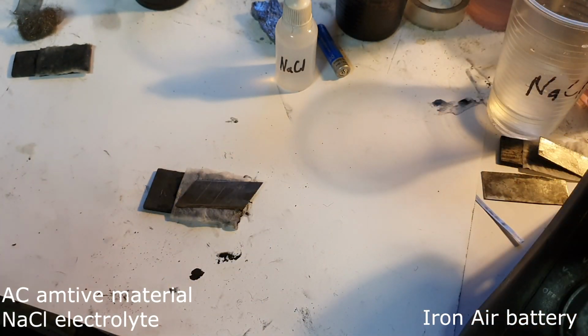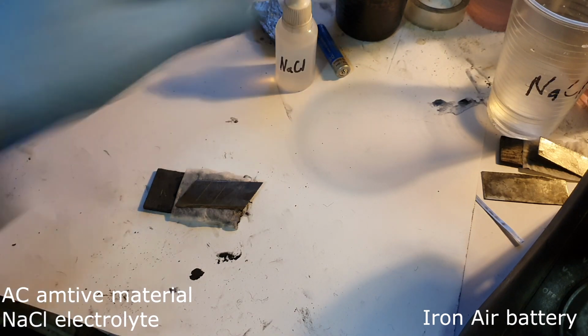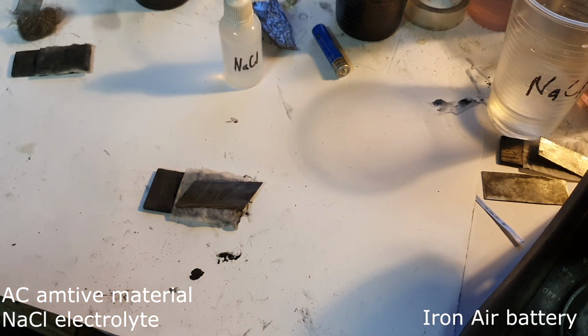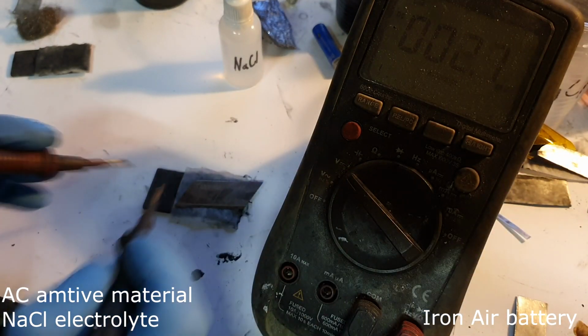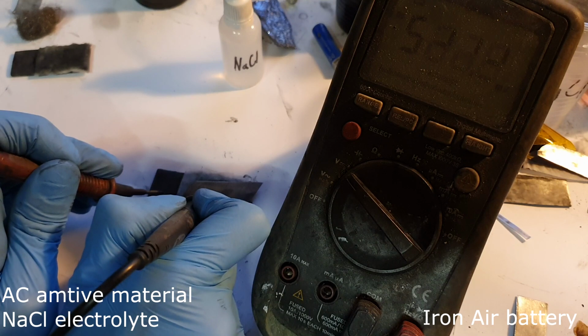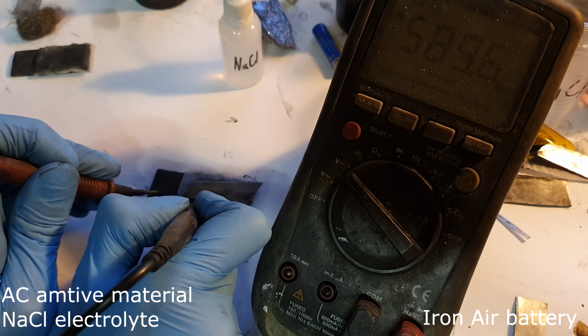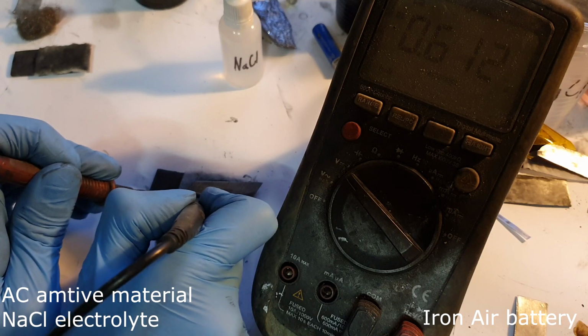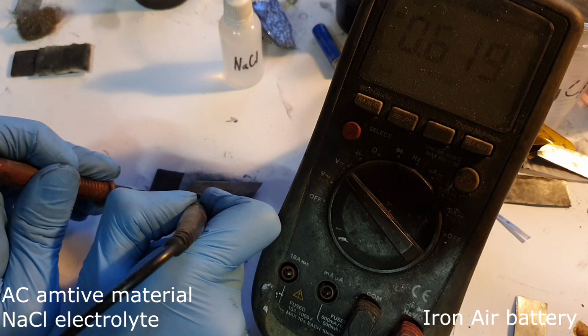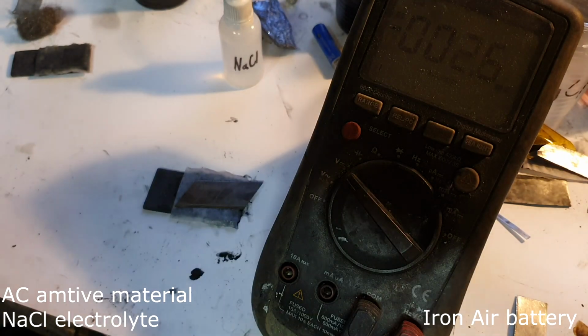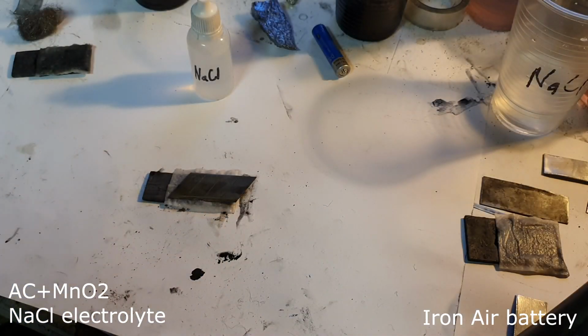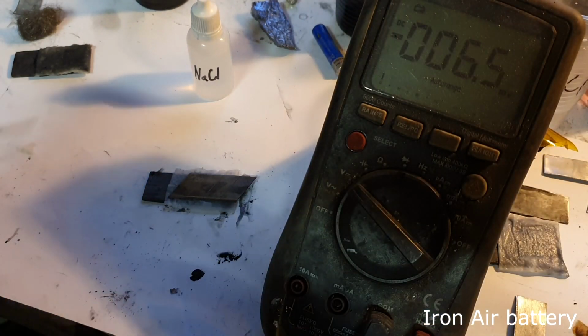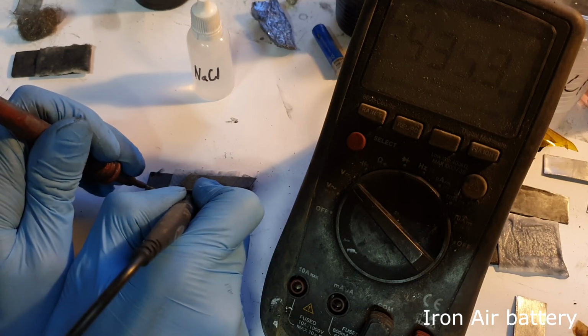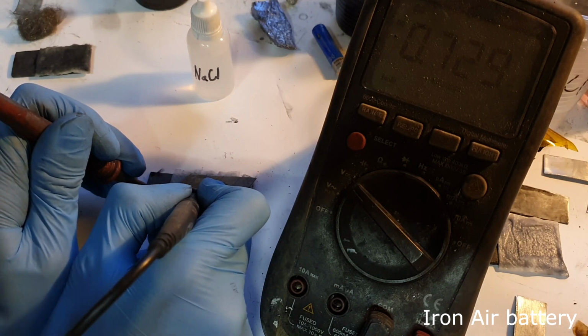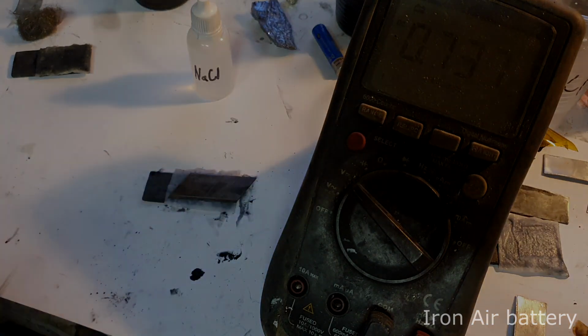And now here I have some iron air battery with sodium chloride electrolyte. And I get 0.6 volts with sodium chloride. This iron air battery has a small amount of manganese dioxide. Let's see if we get a little bit better voltage. And no, 0.73 volts.